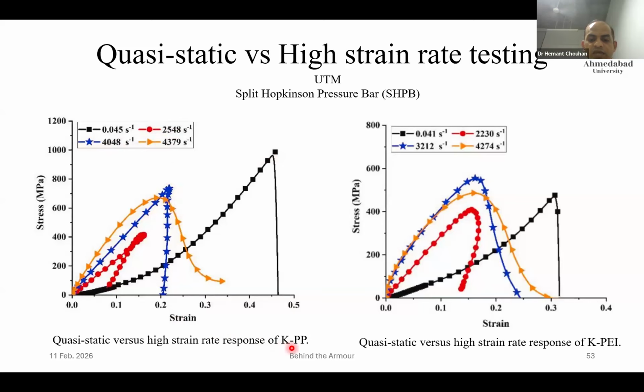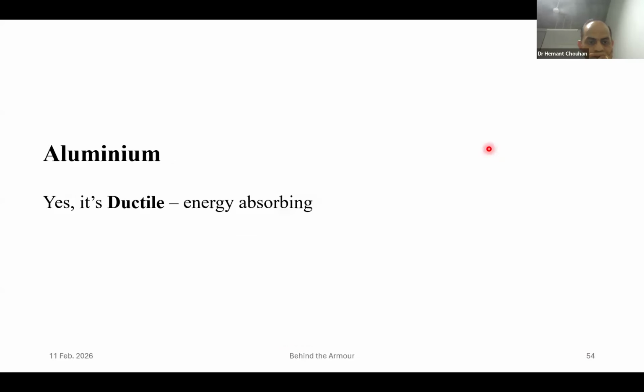Now, for the same Kevlar polypropylene, this is Kevlar 129, if I change the matrix from polypropylene to polyetherimide, which is a very hard and brittle polymer, your quasi-static data has gone down and the high strain rate data is still constantly moving up as we move from somewhere around 2000 to 4000 plus strain rates.